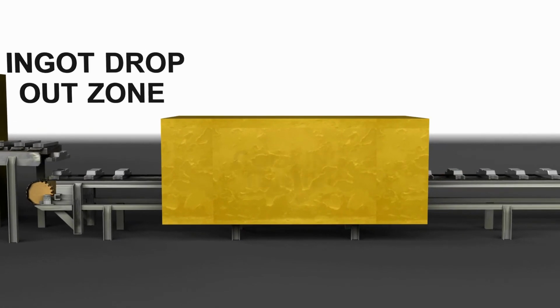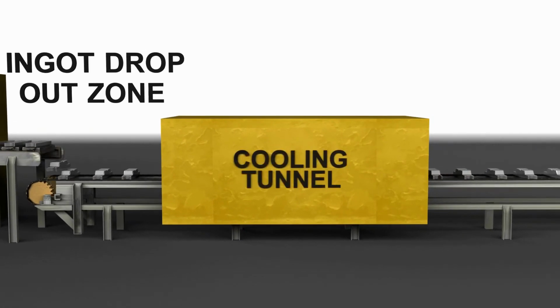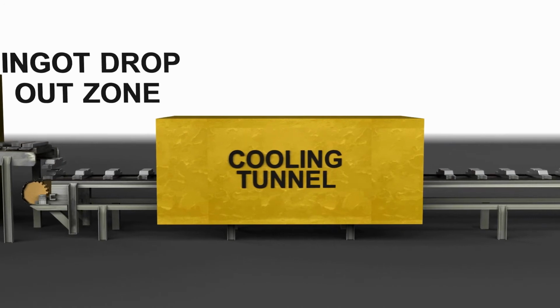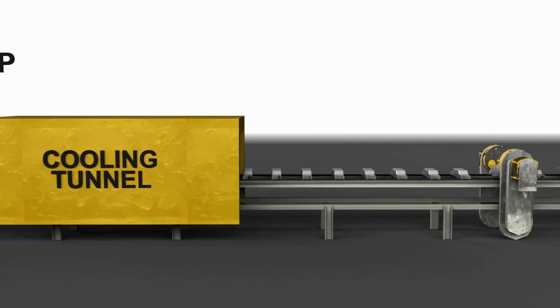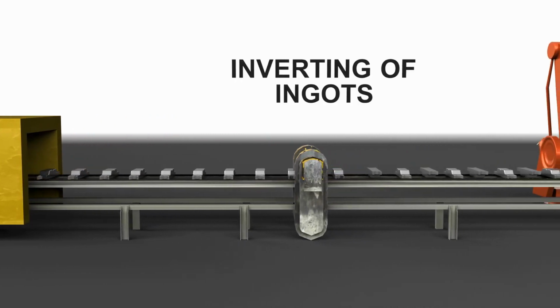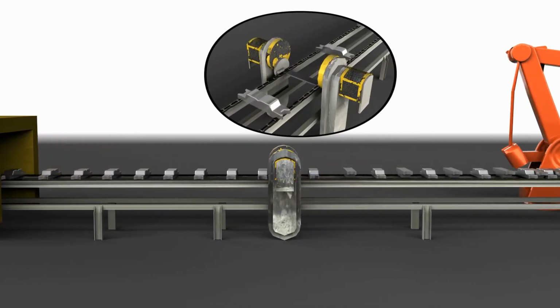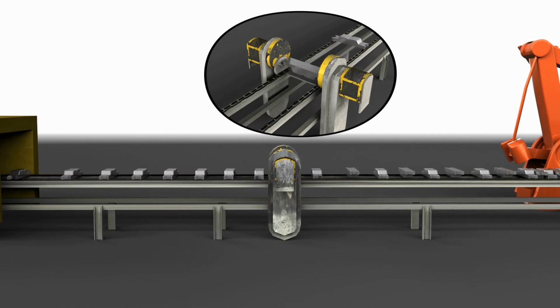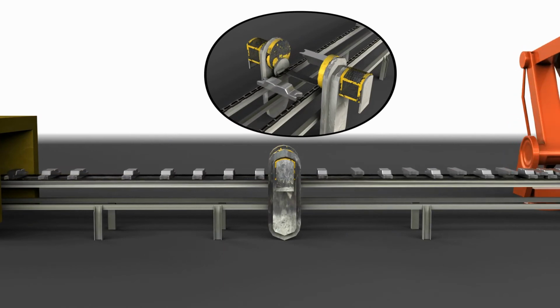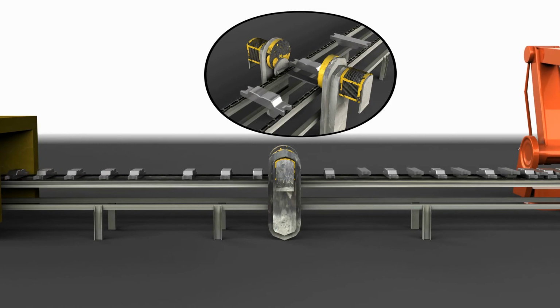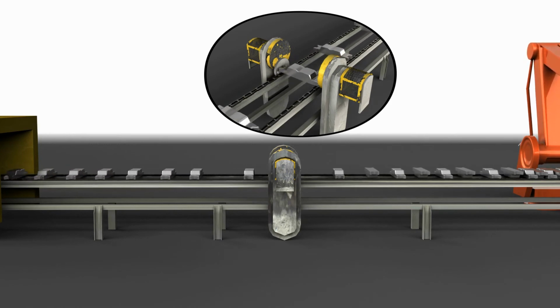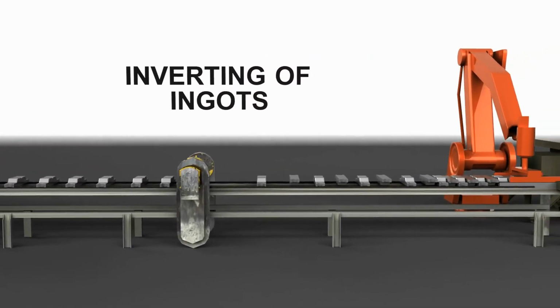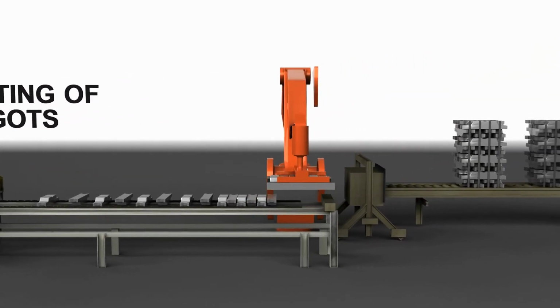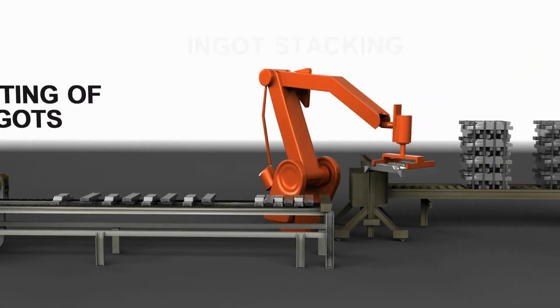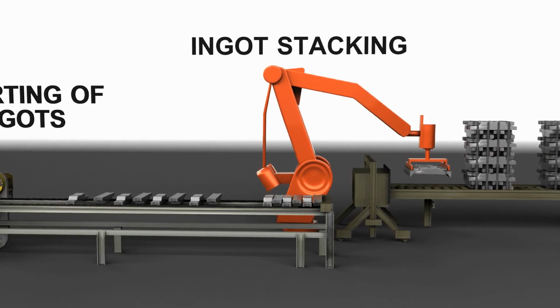Although solidified, the ingots are still extremely hot and now enter a cooling tunnel before they can be handled. After emerging from the cooling tunnel, every other ingot on the conveyor is inverted to ensure that the ingots interlock correctly when they are stacked into bundles. Stacking is carried out by a pre-programmed robot.